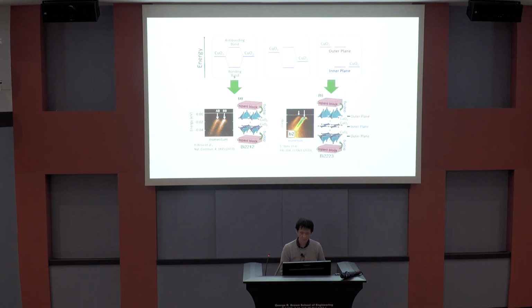In the case of double layer, the coupled double layers are strongly hybridized, so you can observe two band dispersions corresponding to antibonding and bonding. But in the case of the multi-layer system, the potential of the coupled layers become different, so finally you can expect these two layers to be totally separate. In ARPES, you can observe this kind of two dispersions, similar to the double layer case.